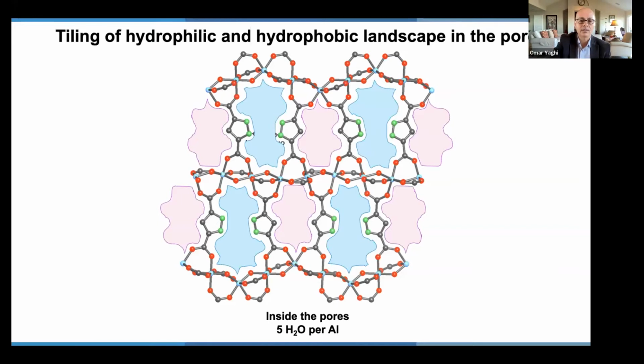So if I'm a water molecule, I first go to the hydrophilic regions, and then I'm bound by hydrogen bonds to the framework. And then the structure is building up across the hydrophobic region to the other hydrophilic regions. So you have water growing inside the structure, and the balance between the hydrophilic and the hydrophobic region allows you to also adjust how tightly water is bound into the framework.